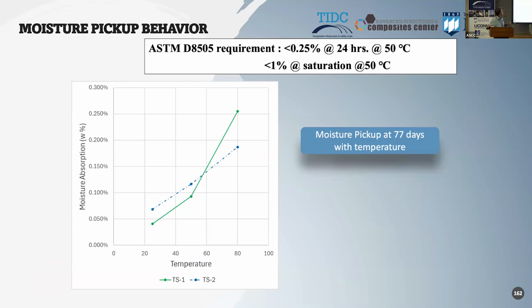Next. We look at the moisture pickup over time. These are the 2 polymers, TS1 in green, TS2 in blue. There is a pickup that happens as a function of temperature. This is for 24 hours, but that moisture pickup is well below what the standard requires, meaning they're behaving as expected. They're meeting that requirement. We should have no concerns about moisture expansion or moisture absorption leading to any degradation. Next.